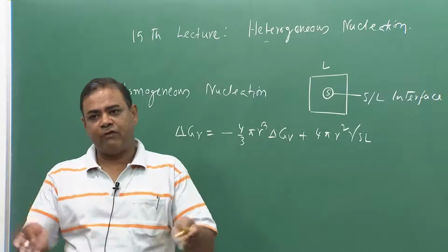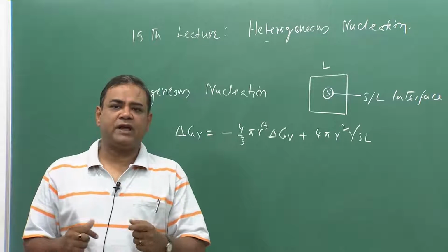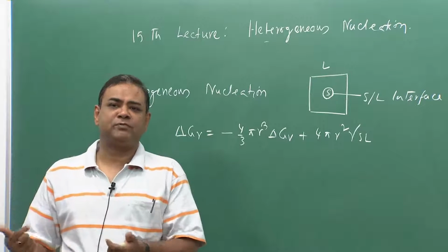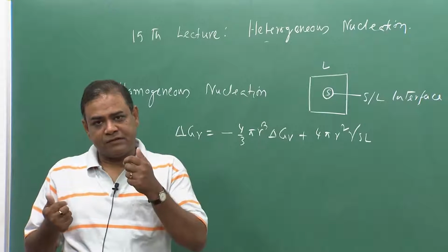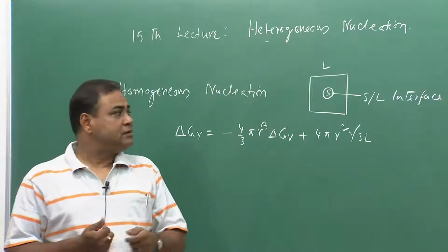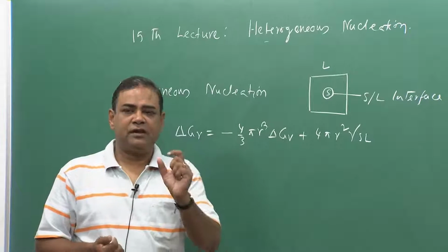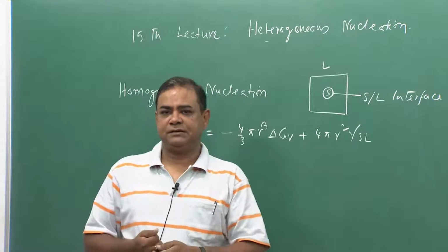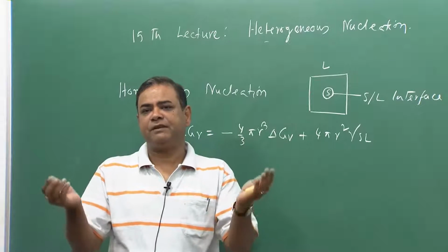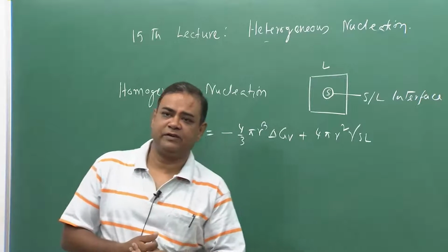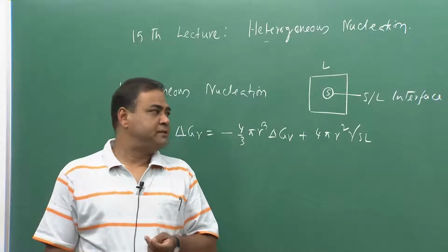If we avoid the container or mold, I can create an instance where I do not have any assistance from mold surface. So, if we do not have any mold surface assistance, the solidification mode would be a homogeneous mode, and people do levitation study. So, the liquid metal droplet is created, and the droplet does not have any mold surface, it is a containerless solidification. There we do experience homogeneous nucleation.